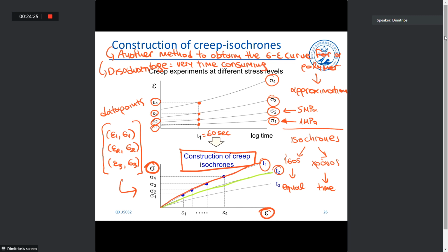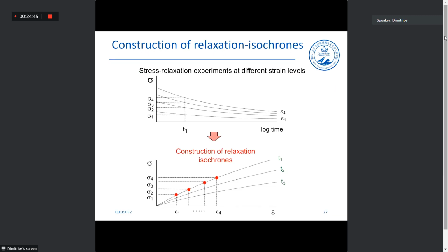I repeat, what we do is we perform creep experiments at constant stress and we measure strain over time. And at a constant time, we get data points of strain over stress, given that we know both of them, and we construct these creep isochrones. In the same way, we can fabricate the relaxation isochrones. In this case, we keep the strain constant.